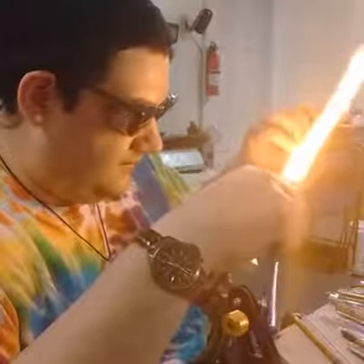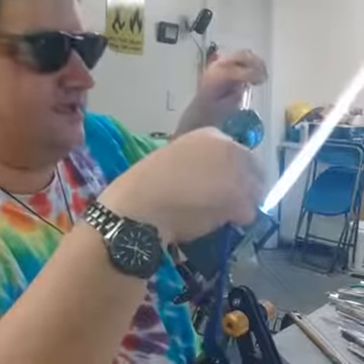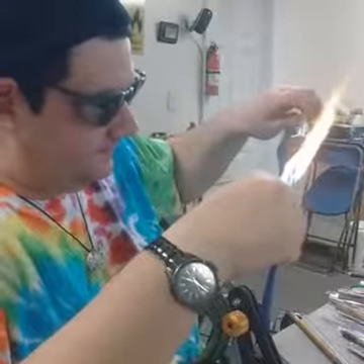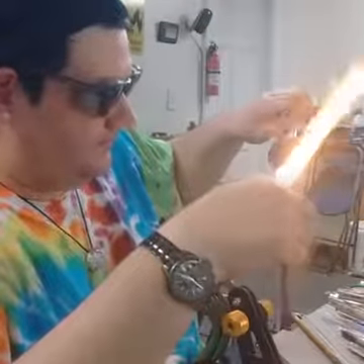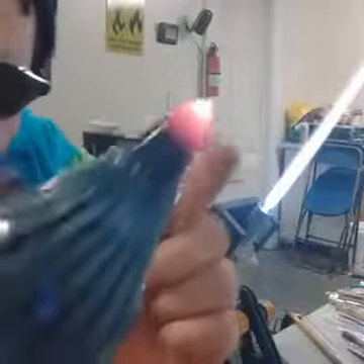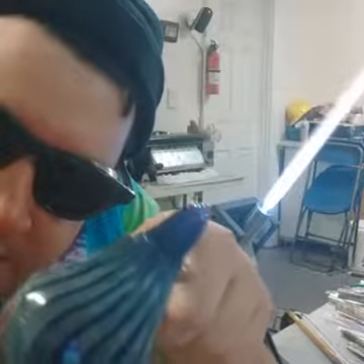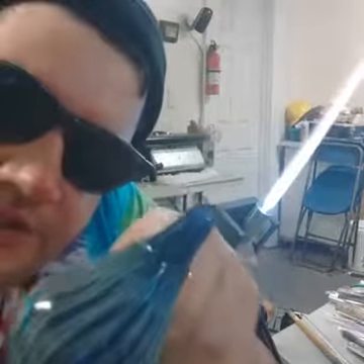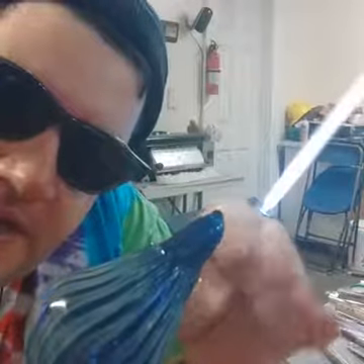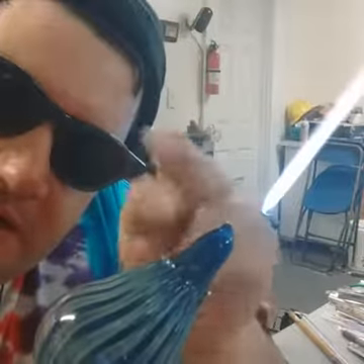Yeah, so. There again, I just welded up a blow tube to the other end, the end that I just popped a hole in. That's where we're at. Now notice where I've melted. I melted down here, and the reason that I did that is because up here, see how all of these lines aren't melted in yet, how they've got little nubbles on them? That's very stressed, and it's also cold. So I want to give myself the opportunity to get some heat back into this end of the blank before I go into the flame. Because if I went right into the flame right here, it would crack almost every time.